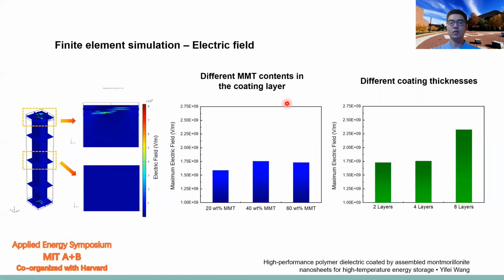In addition to the current density, we also need to pay attention to the electric field strength, especially inside these coatings, because there is a contrast of dielectric constant and conductivity between the MMT, the polymer binder, and the polymer matrix. So we get some localized regions with relatively higher electric field. We see that if we just increase the MMT content, the maximum electric field in the coating layer does not change too much. But if we check the coated polymers with different coating thickness, we find that this sample has a very, very high maximum electric field inside the coating layer.